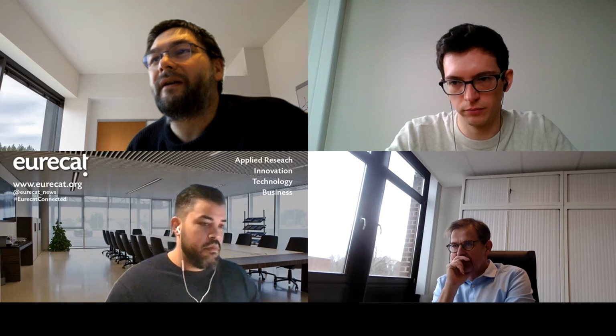I'm here. Aiso Atsuma, indeed, from Tata Steel. For Thomas, you showed the strong dependence on the N value, the hardening exponent, for the necking, the work done in the necking zone. So we make steel here in IJmuiden, and we tend to think that the steel is very strongly strain rate sensitive. And if you have a strong rate sensitivity, your neck is also larger than you would expect. So did you also look at that? That's a big difference, for instance, with aluminium. And maybe that explains the last noise that you still have, or what do you think about that?